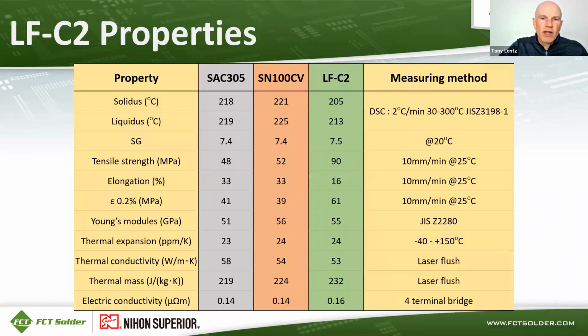Here are the properties of LFC2 as compared to SAC305 and SN100CV, just for reference. I'm not going to read through this table because I don't want to bore you with all of the numbers and data here. Just for a quick highlight though, the melting points of these alloys for comparison. In this particular test, SAC305 was measured to have a melting range of 218 to 219. Typically it's written as 217 to 220C in most literature. SN100CV has a melting range of 221 to 225, but it is reflowable in a profile that's identical to SAC305. And then LFC2 has a slightly lower melting range, which is 205 to 213C, and that would enable the use of a slightly cooler reflow profile.